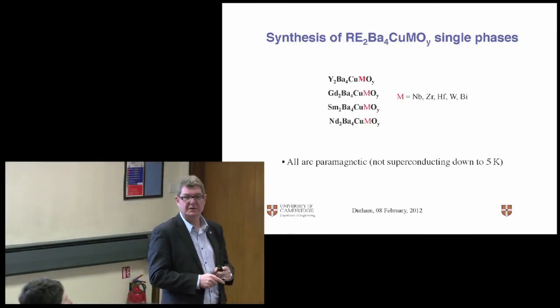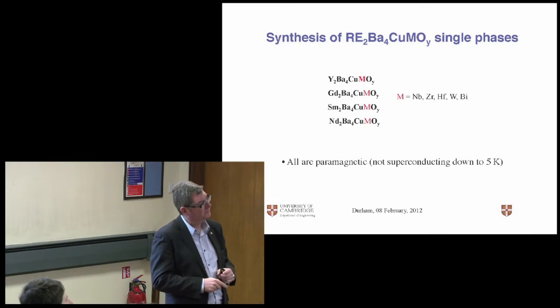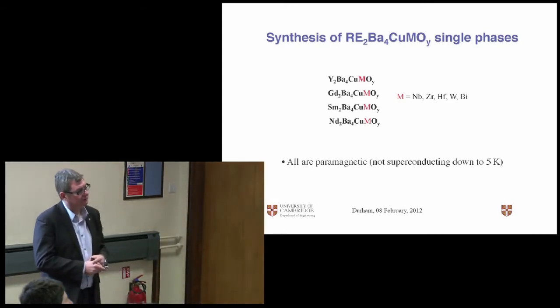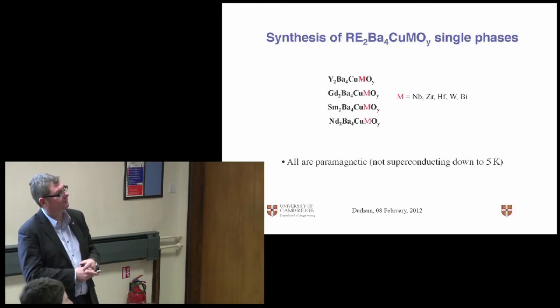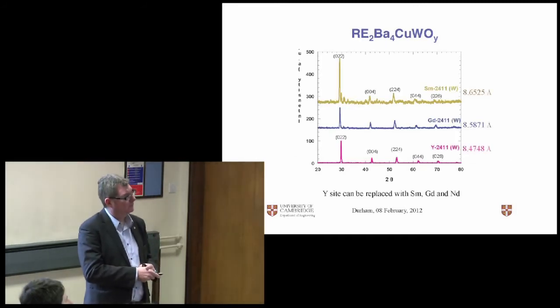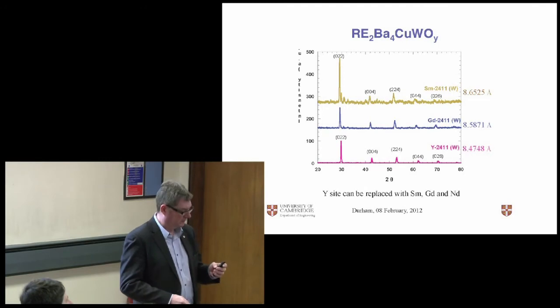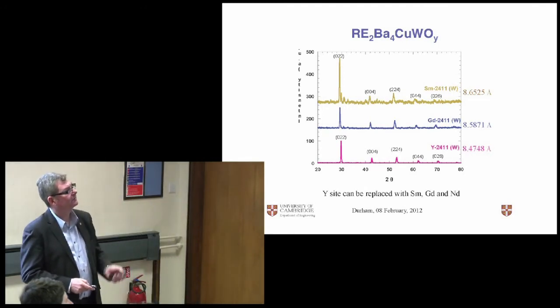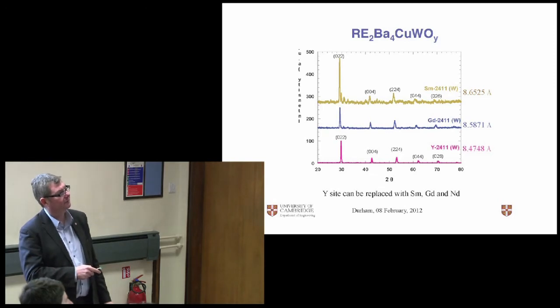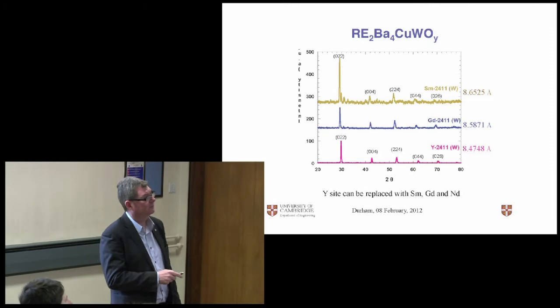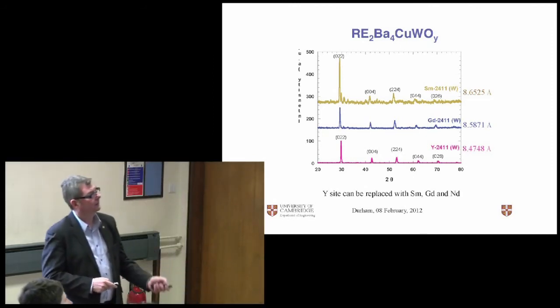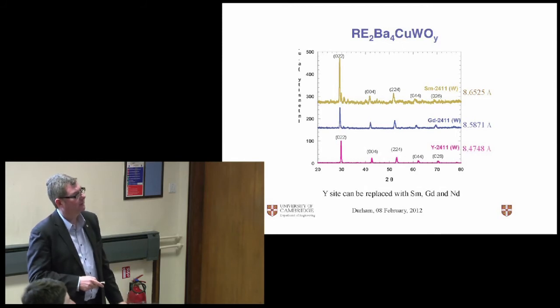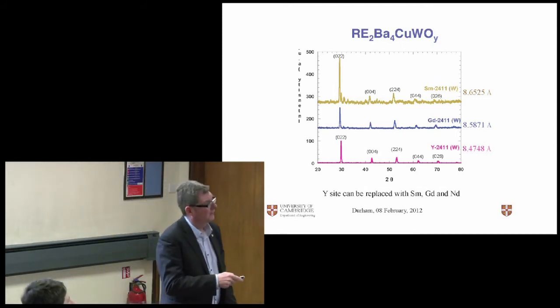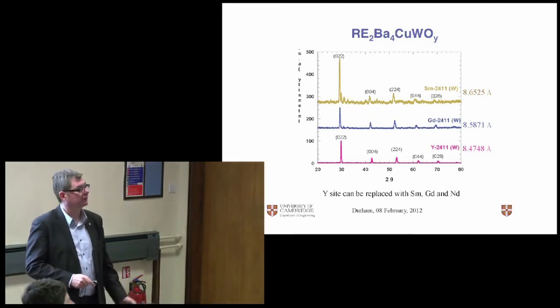We've subsequently found 48 compositions with a whole bunch of different M elements that form single phase material. And from the XRD trace, you can see they're all single phase. So we've got the zirconium, the bismuth, the tungsten, the niobium variants. And they're all double perovskite, so you get a slight variation in lattice parameter, but they're all stable, and we can make them all in single phase form. Better than that, we can change the rare earth element. We can go from yttrium to gadolinium to samarium to neodymium and make 2411 phases out of all of them. And again, these are just some of the others: samarium, gadolinium, and yttrium. Some traces are cleaner than others, and we can control the lattice parameter very accurately.